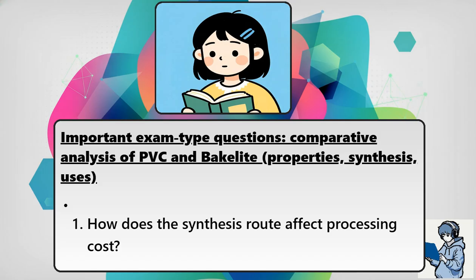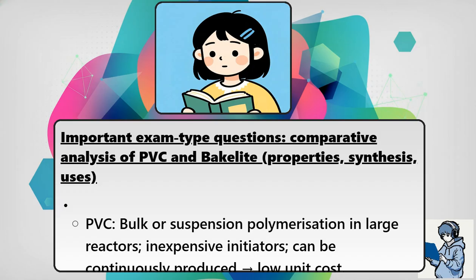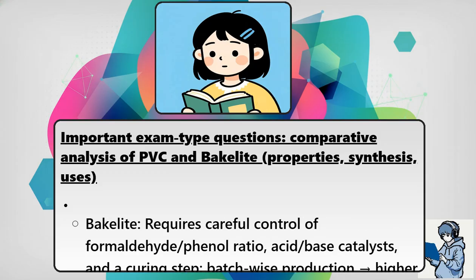6. How does the synthesis route affect processing cost? PVC: bulk or suspension polymerization in large reactors, inexpensive initiators, can be continuously produced, low unit cost. Bakelite: requires careful control of formaldehyde-phenol ratio, acid-base catalysts, and the curing step. Batch-wise production means higher cost, but the end product's heat resistance justifies it for specialty uses.